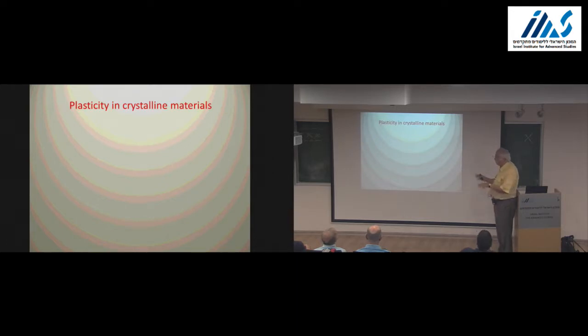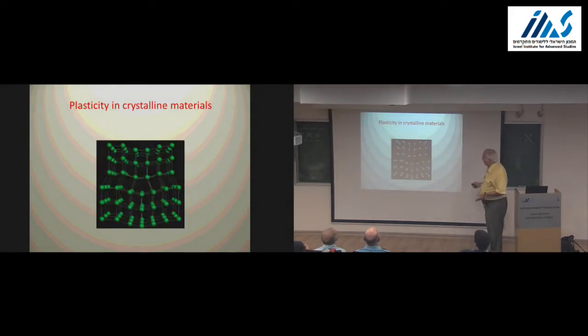So let me, before I go to this, make a little 5-minute digression to what plasticity is at all in crystalline solids, to help Alan next time to explain what an STZ is. Okay, at least at temperature zero. So for a crystalline thing, we know it's a glide of dislocations, it's a glide of defects. Every crystalline material at finite temperature, due to entropy, must have defects, especially dislocations. So when you strain a solid, dislocations glide, it's a non-equilibrium process, it takes out the energy.